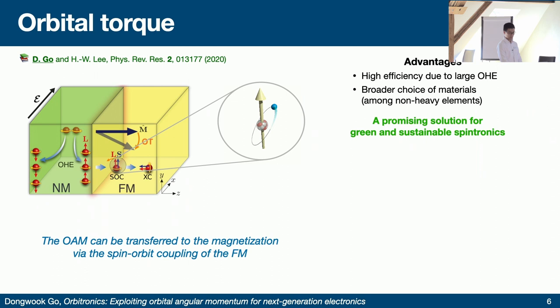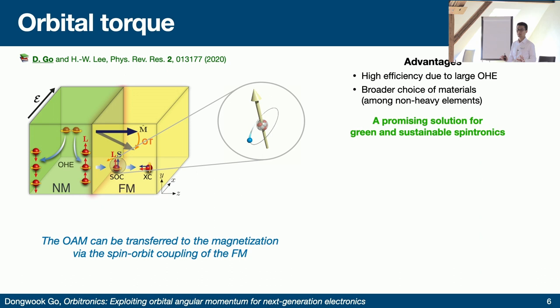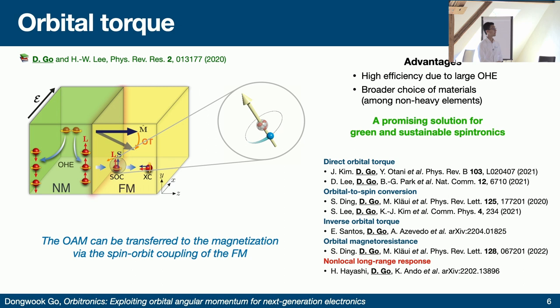This is quite promising because conventional spin-orbit torque applications heavily rely on heavy elements like platinum. But platinum is expensive and scarce. Other materials like tantalum or tungsten in the beta phase show a very large spin Hall effect but are highly resistive, meaning device operation may not be energy efficient. By using orbital current, we have access to a whole different range of materials — we can even choose from light metals or light elements — potentially finding materials that are both energy efficient and have large efficiency.